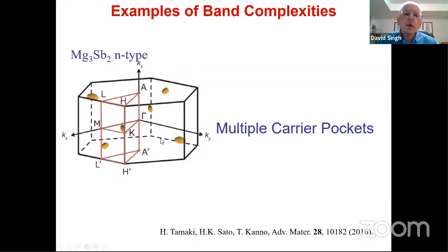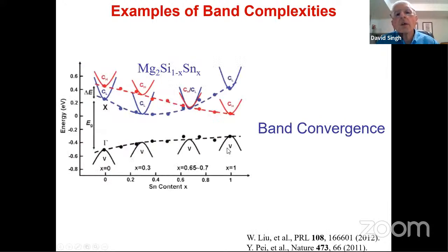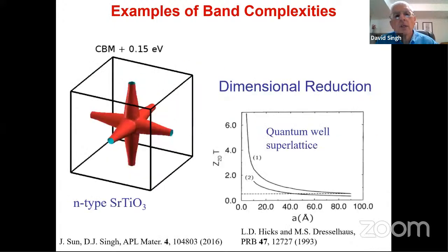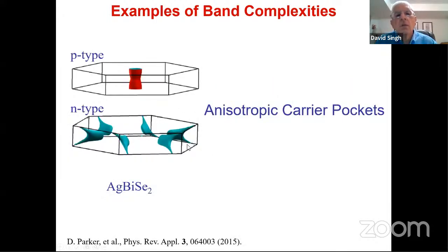We could have multiple carrier pockets. This is magnesium antimony, a very interesting recent experimentally discovered material that was previously theoretically predicted as N-type, and kind of dismissed by experiment as saying it's impossible to achieve N-type. And then some experimentalists tried hard and achieved N-type and showed it was a very good thermoelectric. You can have other kinds of complex band structure. This is a concept called band convergence, where you have multiple bands that come close in energy and then can yield complex band structures. This is some other kinds of isosurfaces that come from degenerate bands, and so on. Here's just another material with very anisotropic carrier pockets, silver, bismuth, selenide.